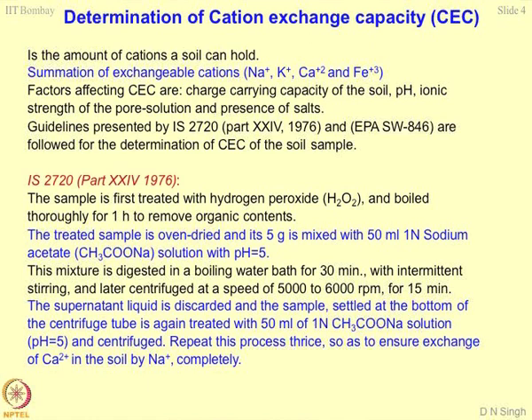So, the treated sample is oven dried, 5 gram, and it is mixed with 50 ml of 1 normal sodium acetate solution with pH 5. Now, this mixture is digested in a boiling water bath for 30 minutes with intermittent stirring and later centrifuged at a speed of 5000 to 6000 rpm for 15 minutes. The supernatant liquid is discarded and the sample settled at the bottom of the centrifuge tube is again treated with 50 ml of 1 normal sodium acetate. CH3COOH is acetic acid, so CH3COONa is sodium acetate solution, again with pH 5, and centrifuged. Repeat this process thrice so as to ensure exchange of calcium ions in the soil by sodium ions.